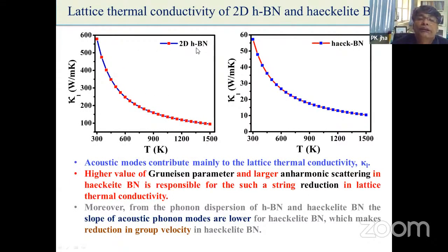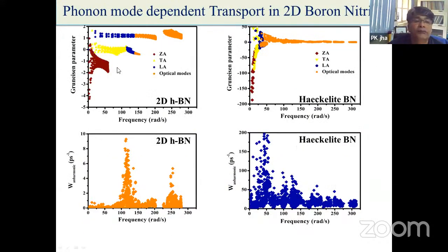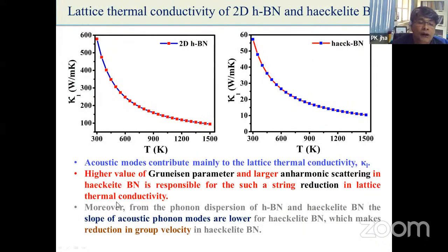Now here you see for the 2D hexagonal boron nitride and haeckelite boron nitride, the lattice thermal conductivity is high at room temperature. It is around 600 watt per meter Kelvin, while in the case of haeckelite boron nitride, you have only up to 60. So what is the reason for that? Acoustic modes contribute mainly to the lattice thermal conductivity, right? That we have seen from here. That is the major contribution is from the acoustic phonon modes, right? So the higher value of Grüneisen parameter and larger anharmonic scattering, which we have seen in haeckelite boron nitride, is responsible for lowering the lattice thermal conductivity.